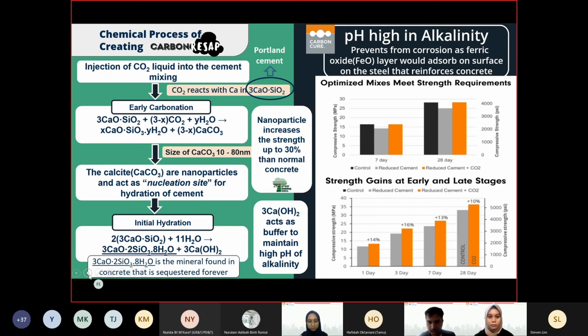The initial hydration stage is where we obtain hydrated calcium silicate, which is the mineral found in the concrete. Note that calcium hydroxide acts as a buffer solution to maintain the high pH alkalinity, which minimizes the possibilities of corrosion in reinforced steel. Also, these nanoparticles result in 30% higher compressive strength than commercial concrete according to Green Building Index, Malaysia. These graphs prove as evidence that explains how CO2 mixed concrete is stronger and aligns with the standardized strength requirement in construction.